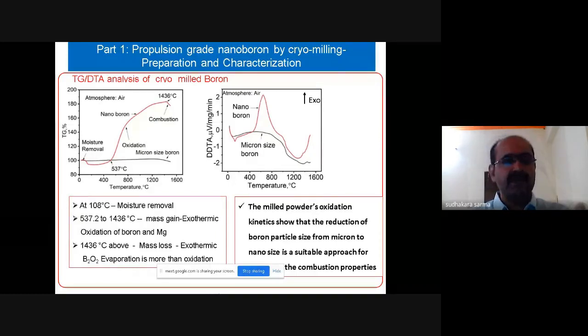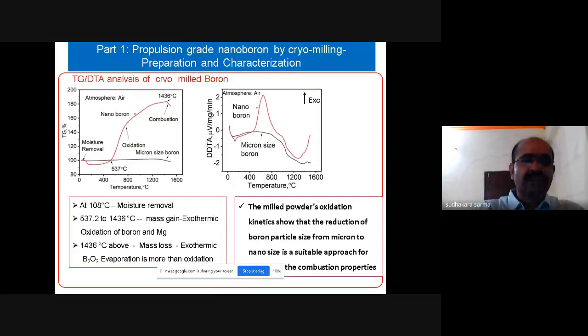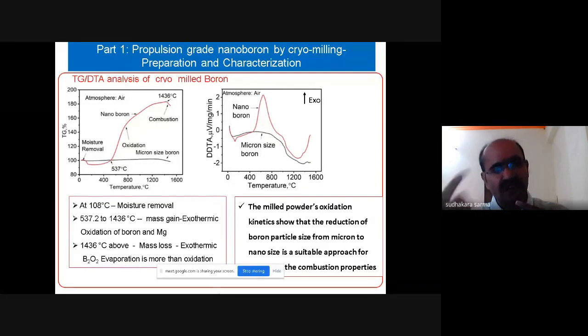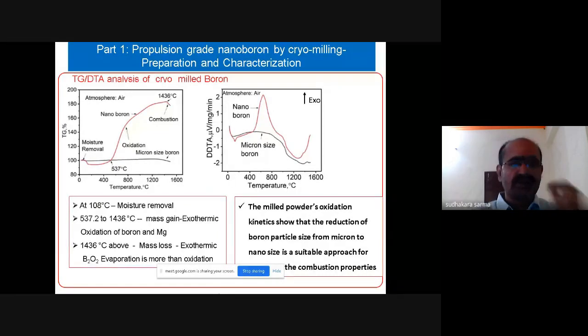a better corresponding exothermic reaction. Here we can see at 108 degrees centigrade, while heating the nanoboron powder, moisture is removed. We can see at 100 degrees centigrade one small peak, and at 537 to 1436 degrees centigrade, the large mass gain is there, and the exothermic reaction can also be seen in the DTA curve. The reason is the oxidation of the nanoboron. At 1436 degrees centigrade we can observe the mass loss. The reason is that while heating the nanoboron, one is oxidation and another is evaporation of the nanoboron. If evaporation of nanoboron is more than the oxidation, there will be a mass loss. That's what is represented here, showing the curve going down. A similar peak we can observe at 1436 degrees centigrade, exothermic reaction.